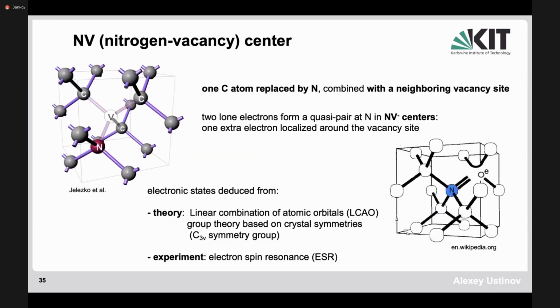So imagine that you irradiate diamond with some high energy particles. This could be, for example, nitrogen ions, or could be also something else. Or you could, for example, put the diamond piece into a nuclear reactor and then add some nitrogen atmosphere, and then high energy particles will destroy some of the sites in diamond, and then the sites can be occupied by a nitrogen atom. So imagine that you have a regular lattice from which you took away 2 neighboring carbon atoms. And then instead of placing back 2 atoms, you placed back only 1 atom, which is a nitrogen atom, which is slightly larger than carbon, and therefore the neighboring place near the nitrogen stays unoccupied. So there will be basically a vacancy situation.